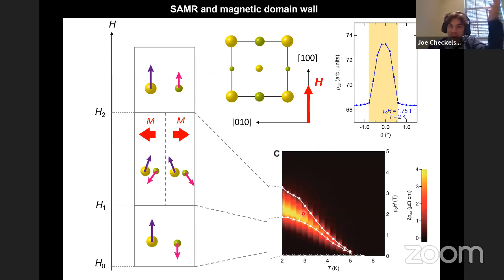in this kind of color plot where you show this enhancement of the resistivity at those domains, we also see an enhancement of the anomalous Hall effect, and it's not one that we can explain in the way it scales just with the magnetization. We had a lot of different ideas about it, which we so far haven't been able to shed any further light on. It could be that just that sheet of electrons which exists at the magnetic domain may carry some Berry curvature associated with the displacement of the Weyl nodes and give a contribution to the Hall effect. Or it could come from some geometric texture or something like that, that's been seen in some related systems. But absolutely, there is a signature of the anomalous Hall effect there.